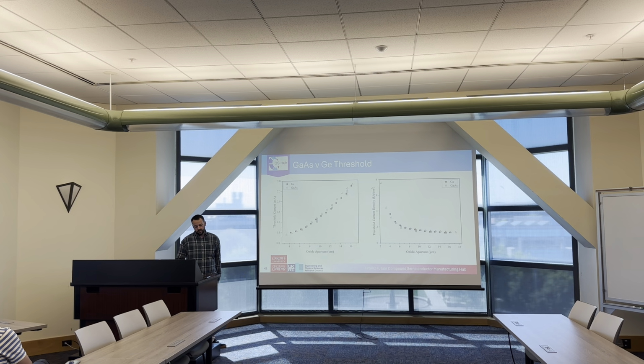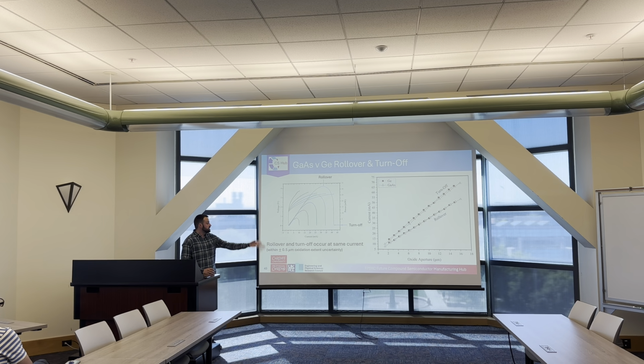So extracting the threshold currents, threshold current densities for devices from the center of a 6-inch wafer. The threshold currents overlap very nicely, the threshold current densities are about the same. Looking then at the rollover and turn-off points, these also overlap very nicely. So it's looking like things are the same between them. And I should say as well, there's a plus or minus 0.5 micron oxidation extent uncertainty, an upper limit of the oxidation extent uncertainty. So when you account for that as well, they definitely overlap.